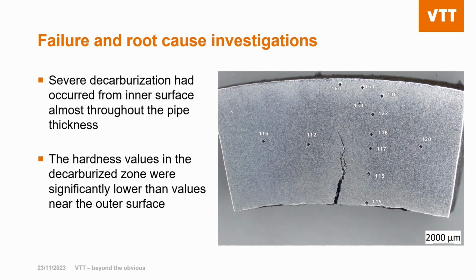Also, severe decarburization had occurred from the inner surface almost throughout the pipe thickness, and the hardness values in the decarburized zone were significantly lower than values near the outer surface. So if we look at the image here, we can see a major crack in the middle, but we can also see decreased hardness values from 110 to 130 Vickers in the decarburized zones. Near the outer surface, we can see hardness values which would be typical for this kind of steel in normal conditions, and those are values of about 160 Vickers.